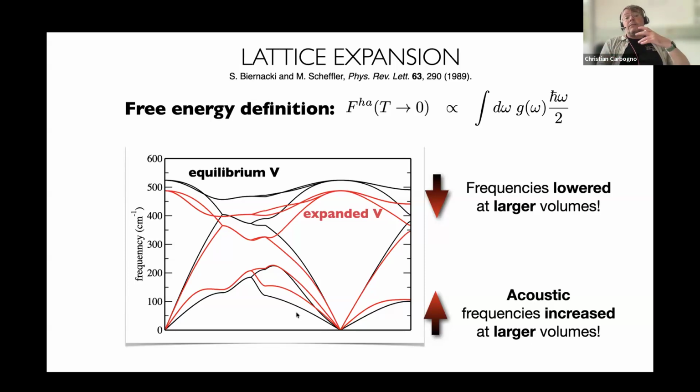The reason why this happens is that silicon has a very specific tetrahedral sp3 kind of electronic configuration where the atoms really want to stick around that position. If you move them out of that very nice coordination, the energy increases and the crystal does not like that. That is an anharmonic effect that you can also account for in so-called quasi-harmonic calculations to account for this lattice expansion.